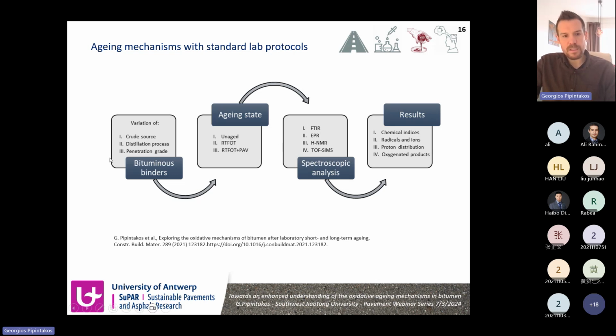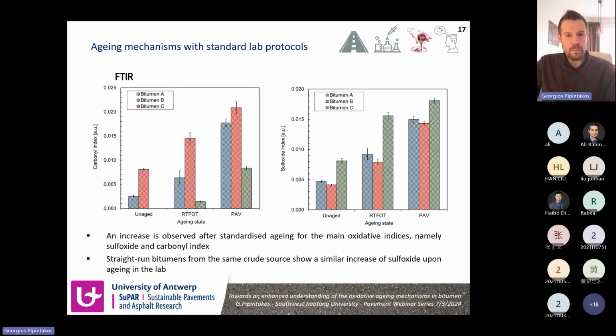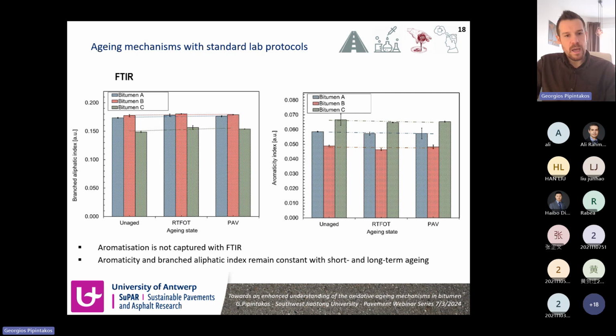So the same spectroscopic techniques and the same binders were used in order to identify the effect of lab simulations on the aging mechanism, and more details of the results can also be found in this publication. The results from FTIR showed, as expected, an increase of both carbonyl and sulfoxides with aging, and the two straight run binders coming from the same crude, binders A and B, showed similar increase of sulfoxides in the lab. This is something that has been reported several times in the literature.